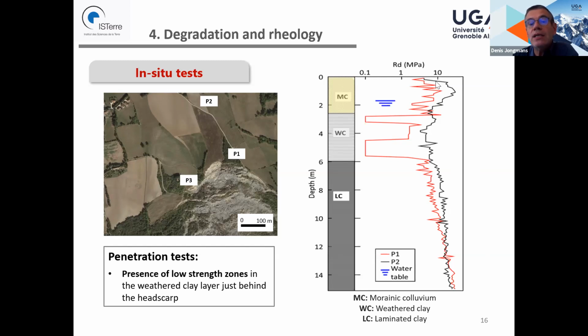And what is striking is the difference between the resistance profile at P2 and P1. Of course, at P1, you see that we have a dramatic drop in strength inside the weathered clay that we observe also in P3. For simplicity, I did not show this information, but we have the same kind of results. So very low, very soft zones, which can reach, you see here, almost 1 meter in this weathered clay. And this was completely new and unknown